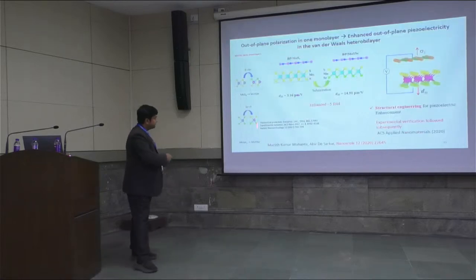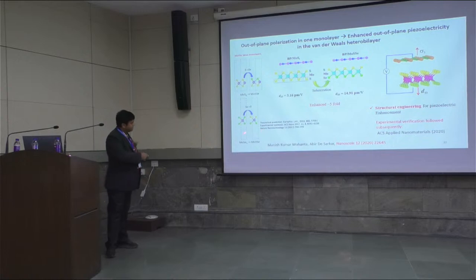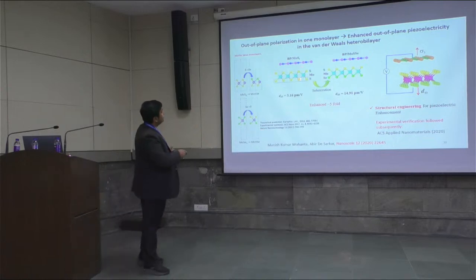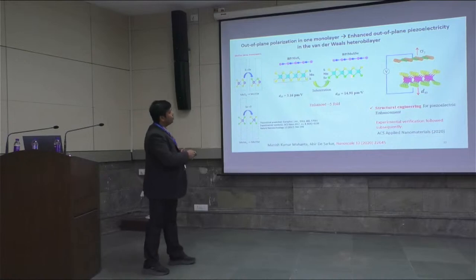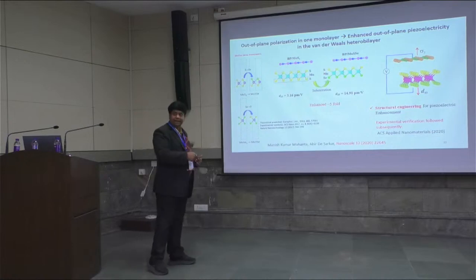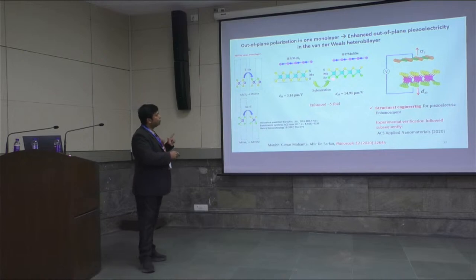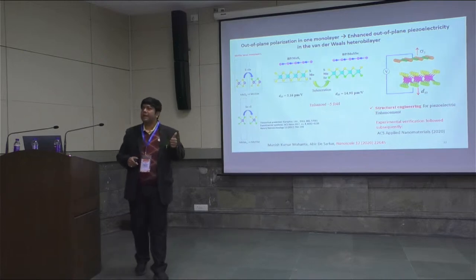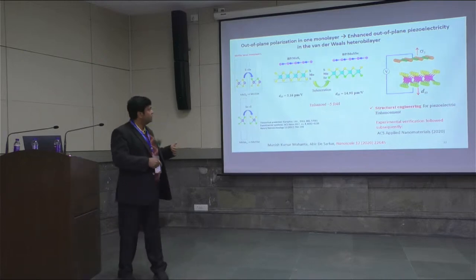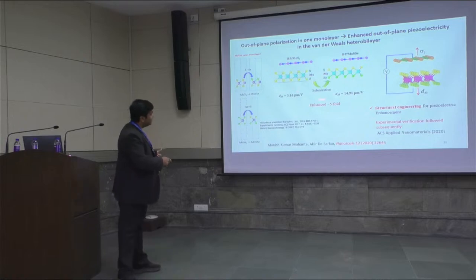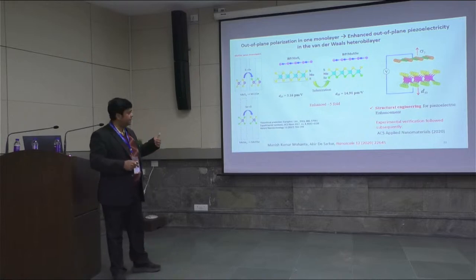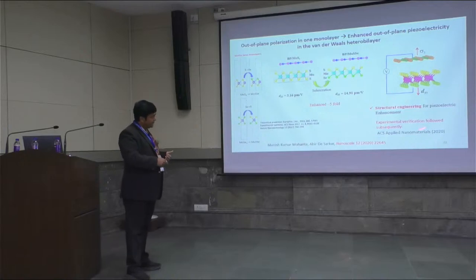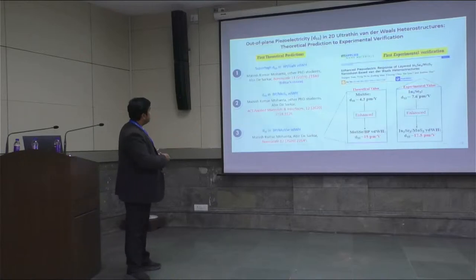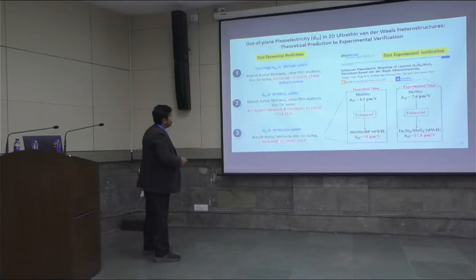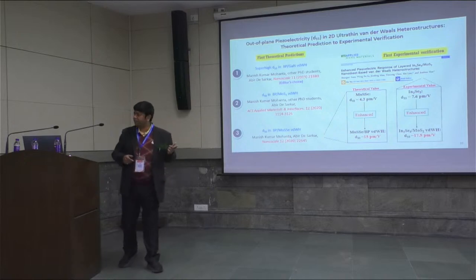Now, moving on. So now Janus structures have been experimentally synthesized. So MoSSe has been experimentally grown, synthesized. So what if we replace MoS2 by MoSSe? So if we introduce a mild out-of-plane polarization in one of the individual monolayers, we find that there is a five-fold enhancement in the out-of-plane piezoelectric coefficient, which has been confirmed experimentally on a similar system.